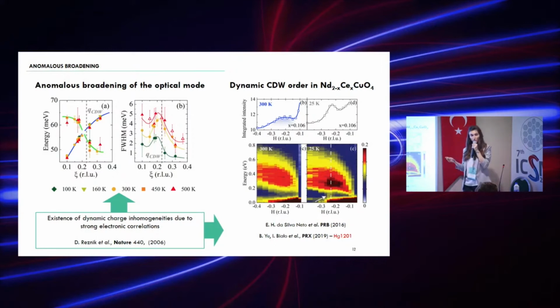So it's a temperature-independent broadening. And then we went back to the publications of Reznik from 2006, and what they are saying is that they predict that some dynamic charge inhomogeneities can cause this kind of behavior, so broadening of phonon modes. And actually, dynamic charge fluctuations, dynamic charge density wave, was seen in neodymium cerium copper oxide. It was published in 2016, and this kind of feature is visible and is temperature independent. And what is more, it's also coupled to paramagnon dispersion. So at the same time, this dynamic charge density wave and paramagnon contribution are increasing in resonant inelastic X-ray scattering spectra, and that's shown on these two pictures.